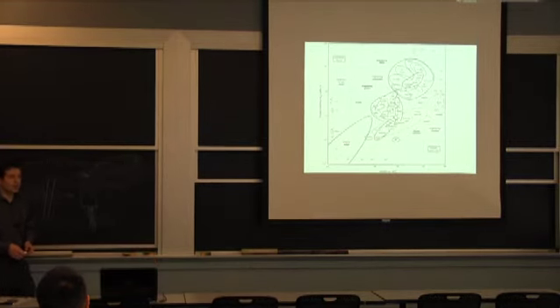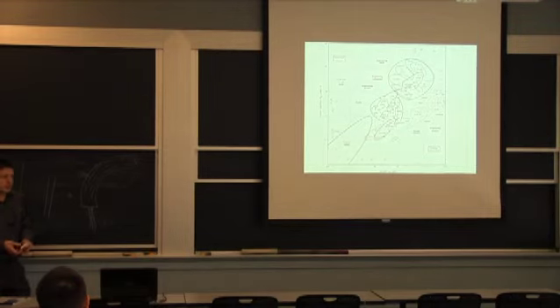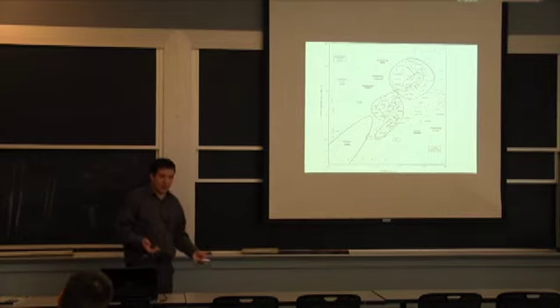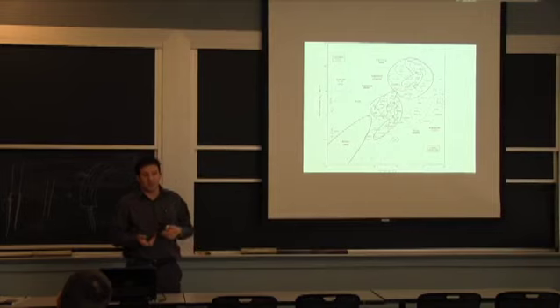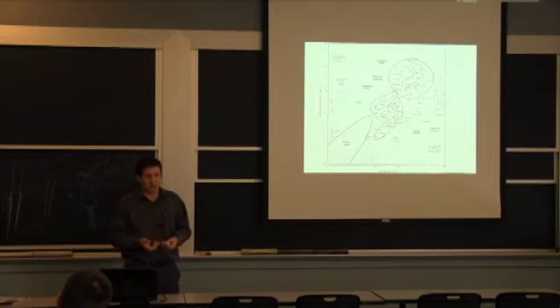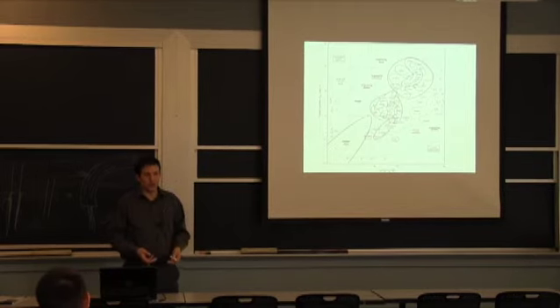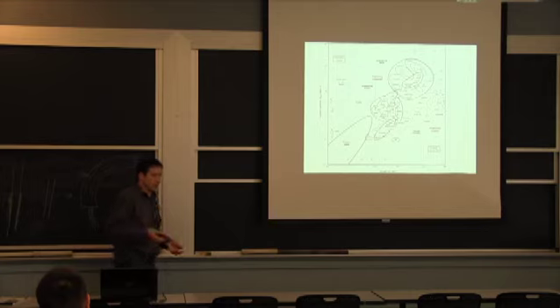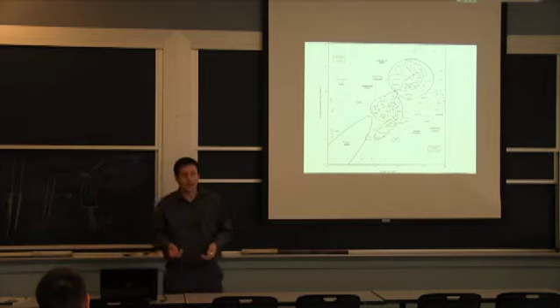But the idea is when you have a plastic, it's harder to use the fracture mechanics background I introduced to you a little bit. It's common to think of it as it will be able to take a fair amount of load, but not necessarily a repeated load, not necessarily a sustained load. If you have a constant load on an unreinforced plastic, you need to design it to allow it to expand. And that's the example with the polyethylene piping that Professor Eger mentioned, that they didn't want to deal with corrosion anymore, so they decided to use high-density polyethylene.